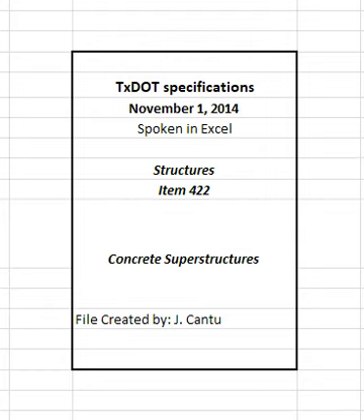4.7.1.2 Wet burlap. Place pre-wet burlap no more than 10 feet behind the finishing operation. A work bridge may be required to avoid marring the surface. Ensure the wet burlap covers the entire surface. Use sprayers, hoses, sprinklers, or other similar methods to keep the burlap continuously wetted until application of the final curing.